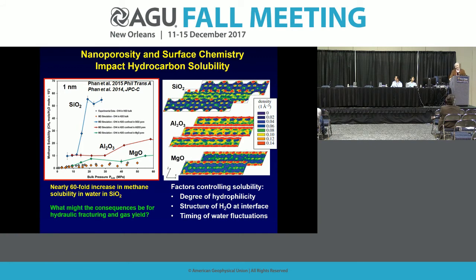Well, there's a number of factors that control the solubility of a particular constituent in water, particularly at a nanoscale, and part of it is the degree of hydrophobicity, structure of water, and the timing of these fluctuations at this length scale. So you see for silica, for example, you look at the density of water on that surface, you see a lot of dark blue. The dark blue is a very low density region on that surface, and so very few high density clustered areas. This allows open space. These low density water regimes offer open space for methane to occupy and increase that solubility. Of course, this changes as the hydrophobicity changes.